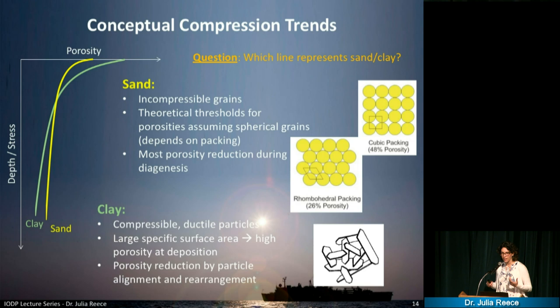They all have extremely platy shapes, so a very different aspect ratio, and they also have forces that make them attract to each other, and so they form these card house structures that have a very high specific surface area and therefore a very high porosity. So these clays can hold a lot of water, and we're talking about 70-80% of porosity on the seafloor.